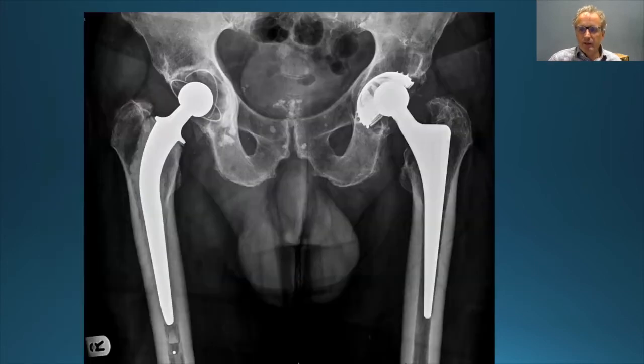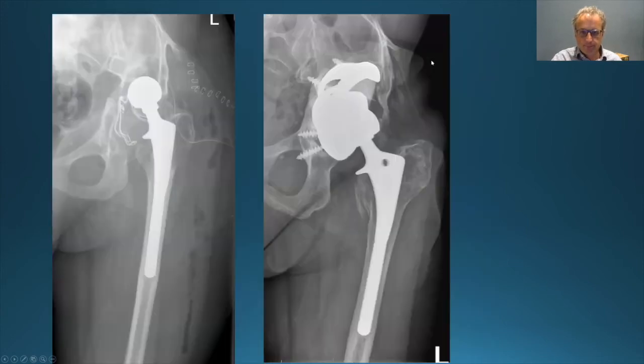On the left here, we've got a cementless implant. I put this in to show the large lytic lesion in here, which is due to osteolysis. You can see there's been volumetric wear. It's against the joint reaction force, perpendicular, so it's volumetric wear rather than linear wear, and it's caused plastic particles that have gone up there. Sometimes osteolysis can be dramatic, and you can get a fracture with the osteolysis, and these are fun to fix.